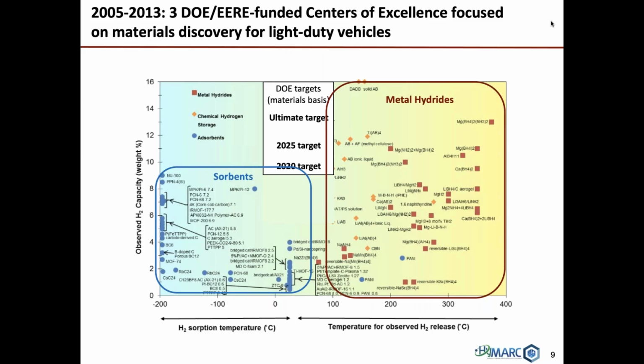And these materials can also achieve rather high gravimetric capacities, but they suffer from exactly the opposite problem from sorbents. In this case, the hydrogen is bound much more strongly to another element, which means that you have to heat it in order to drive the hydrogen off. And the amount of heat depends on the strength of those bonds. There are metal hydrides where you can heat them to 100 C or less. Others require much more. The consequence of that is that if you were doing this on board a vehicle, you might have to burn some of the hydrogen to get the fuel bed up to a temperature where it would release its hydrogen at a rate that would be usable for the fuel cell.